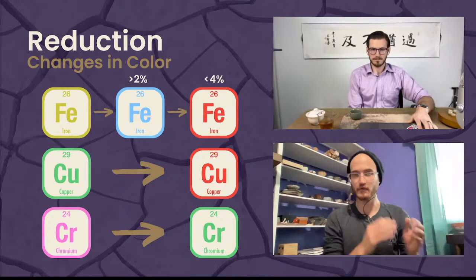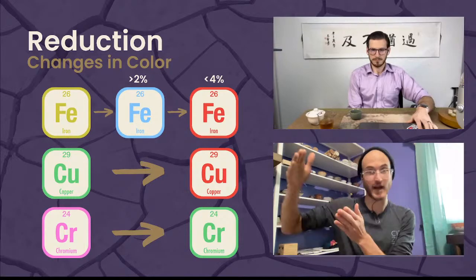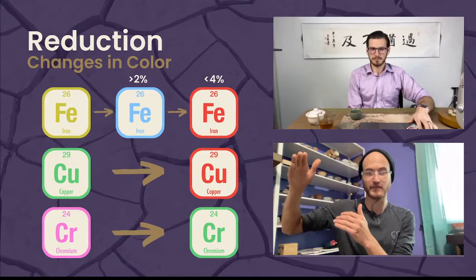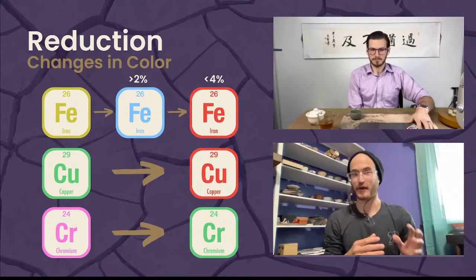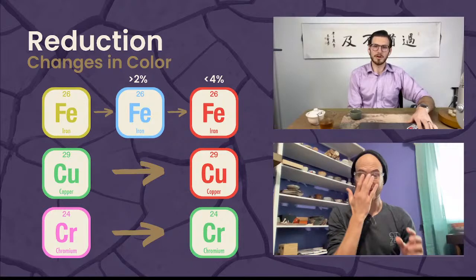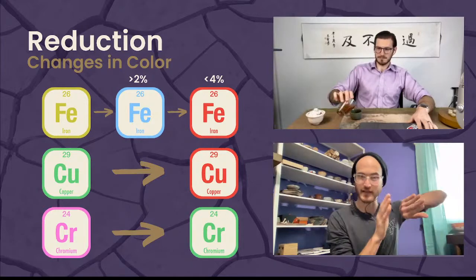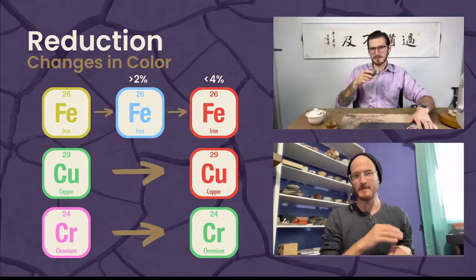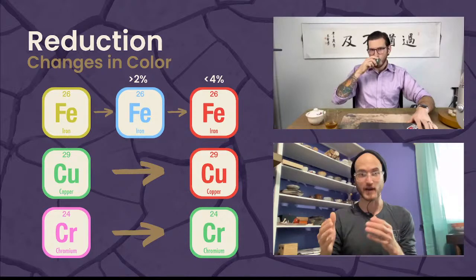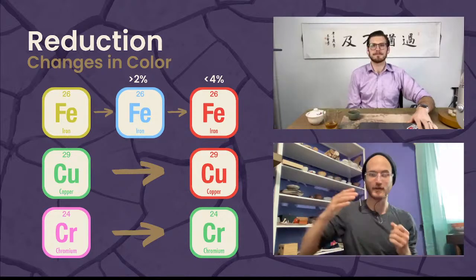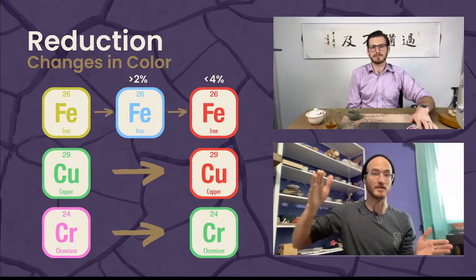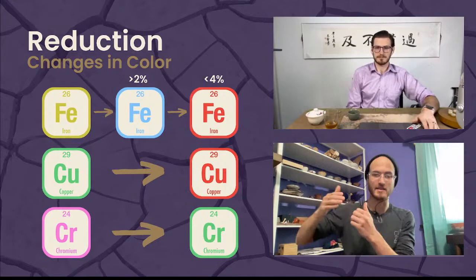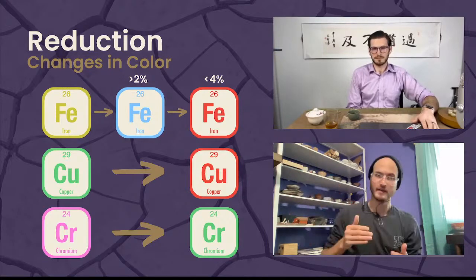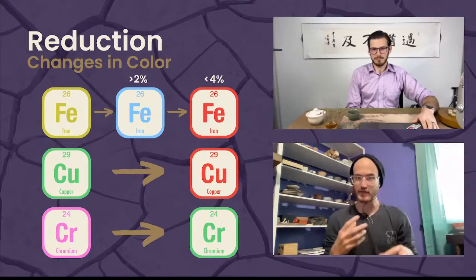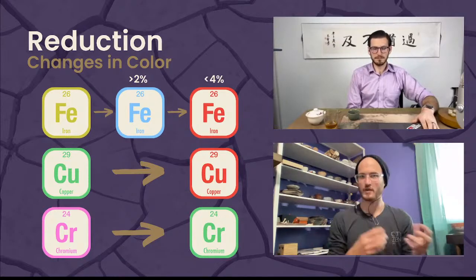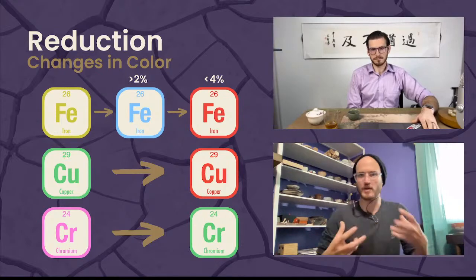But iron in reduction is very stable. So if you reduce the whole firing, and at the end of the firing you want to fire a little bit hotter and clear the atmosphere, the glazes will remain the same, and so will the clay. But copper is very unstable, and it will even aerosolize off of one pot onto another in a firing and cause little flashing spots on pots next to it. If you fire with reduction the whole firing and then end with oxidation, you can actually re-oxidize the glaze and turn it from that red color back to clear or green. So it's really a tricky thing knowing your oxides, how they react to the environment, and what you can do during the firing to bring out the best in those glazes.